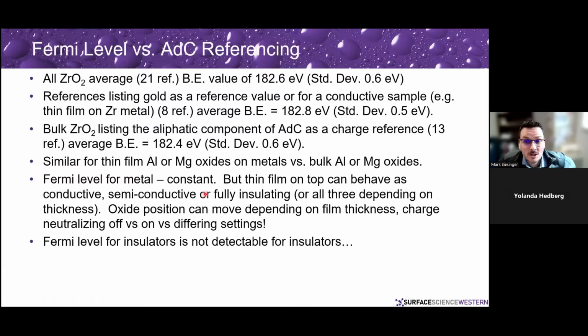So some of the ways to look at this, if I look at the Fermi level versus ADC referencing, if I look at zirconium oxide references from the NIST database, there were 21 references. You get a binding energy value of 182.6 eV with a standard deviation of 0.6 eV for all zirconium oxide samples. If I look more closely at those samples and I see references that are listing either gold as a reference value or a conductive sample, so like a thin film oxide on a metal, those are 8 references, we get a binding energy of 182.8 eV.